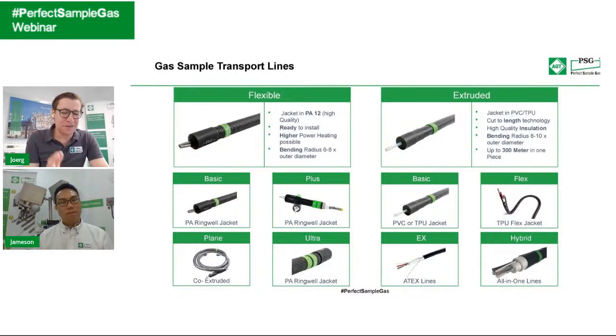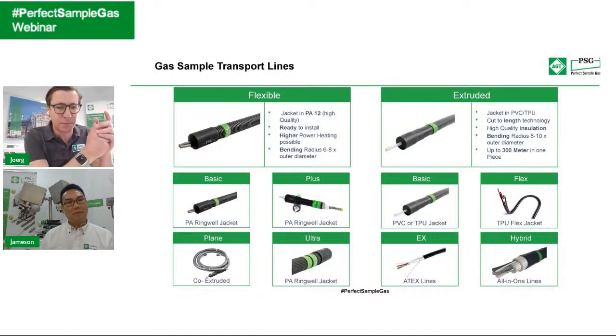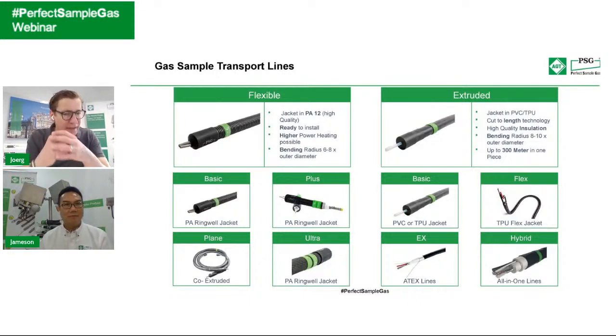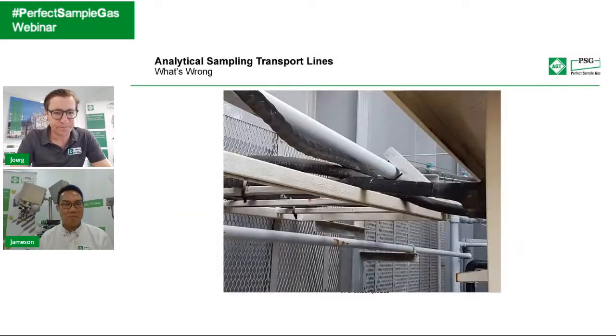Jemson, you don't need to worry too much about this in Singapore, but especially in Europe and other regions, when you have cold outside conditions, minus 10, minus 20 degrees C, for example, that makes this problem quite bigger. If you face issues, for example, in the connection between the heated sample line and the gas sampling probe, there is insulation material available from us, but also from other sources. This can already help you get better coverage and make sure the temperature remains well above the acid dew point.